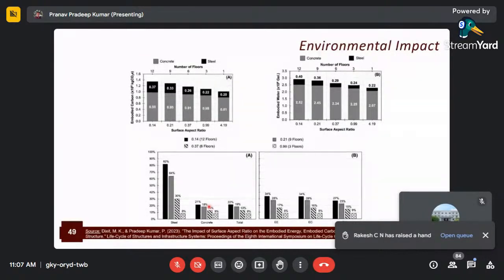And one of the reasons for this could be that the size of the floor slabs is kept constant for all the cases here. That's primarily due to the limitations that we have with respect to slab thickness reduction, which is owing to the vibration issues that these buildings could face, and that could adversely affect the serviceability of the building structure. The B plot here shows a variation in the total embodied energy, embodied carbon, and embodied water for the different aspect ratios.